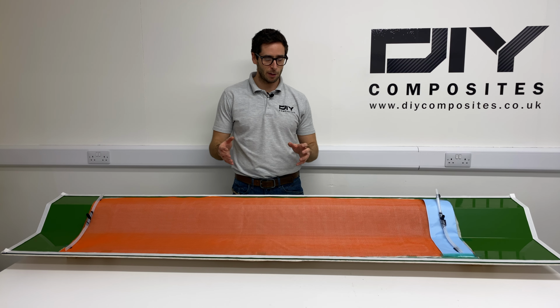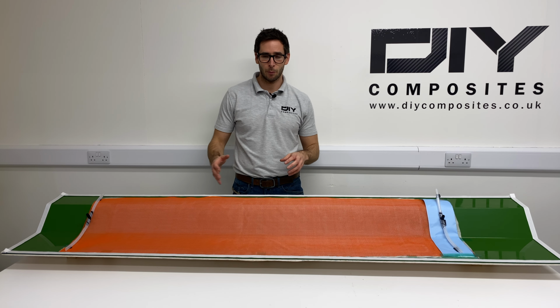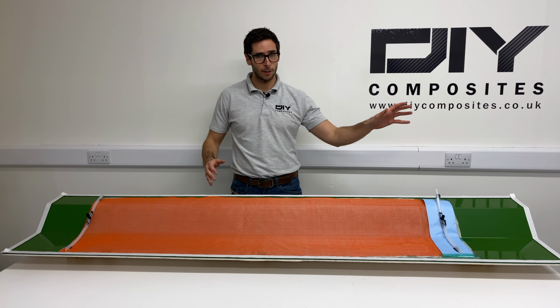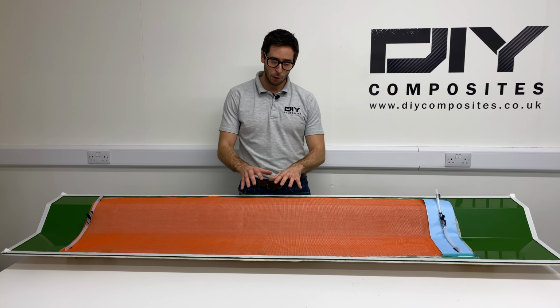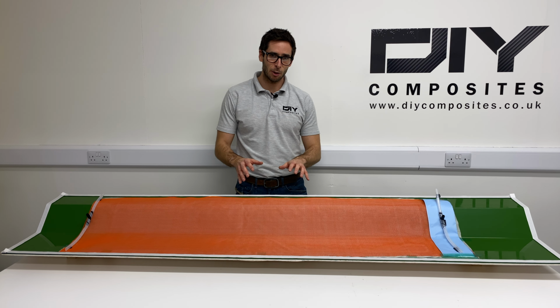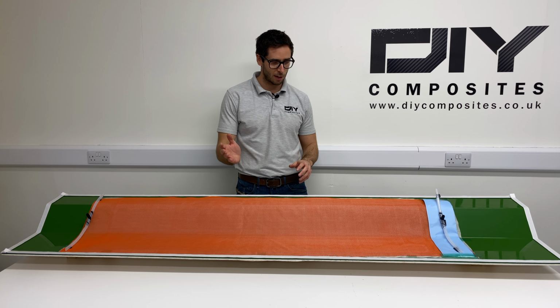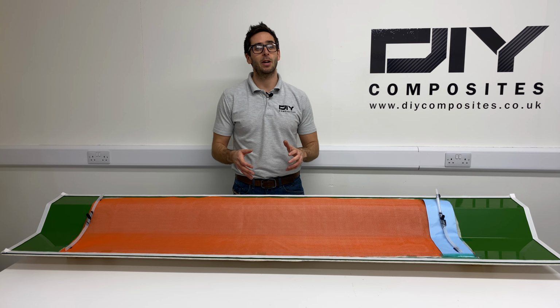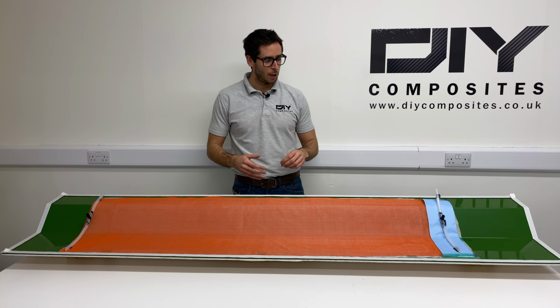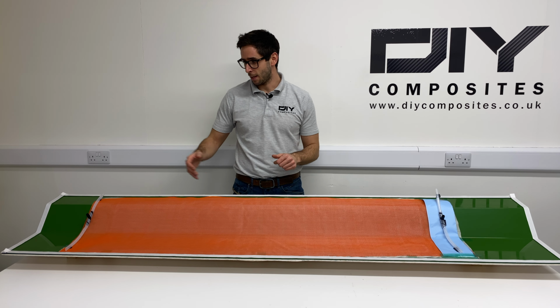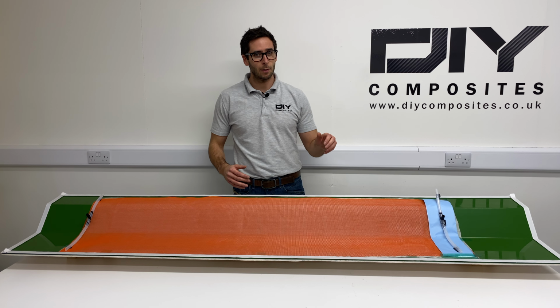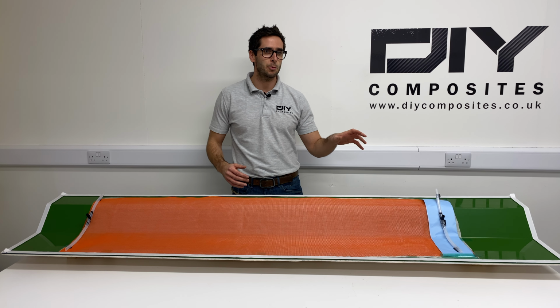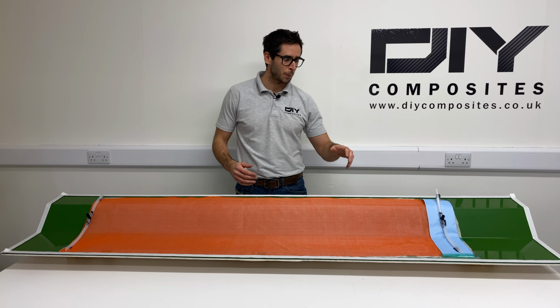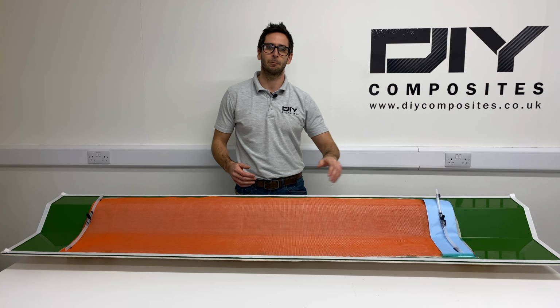In a traditional resin infusion, once the laminate's wet out, the inlet line and the outlet line are shut off, and you rely completely on the integrity of the vacuum bag to keep the laminate onto the mould surface. Any loss in vacuum pressure can lead to part scrappage. By using this membrane, it means the inlet is locked off, but the outlet can still continue to have a vacuum drawn and air is drawn from the bag, but no resin will leave the bag.